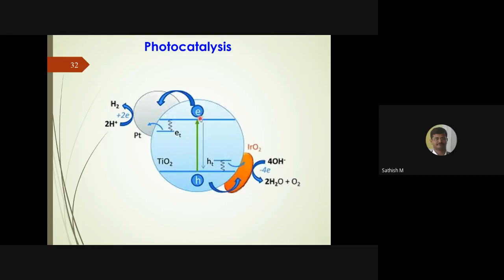So this recombination rate should be lower than the rate at which this electron moves to the other reaction, the reduction reaction. If the rate of that reaction is higher than this, then you can avoid the recombination process. The more recombination you avoid, the higher the efficiency of the process will be. Unfortunately, not more than 20% efficiency is reported for this photocatalysis or photoelectrocatalysis process. I'm just telling the highest value, and most of the processes are much lower than this.